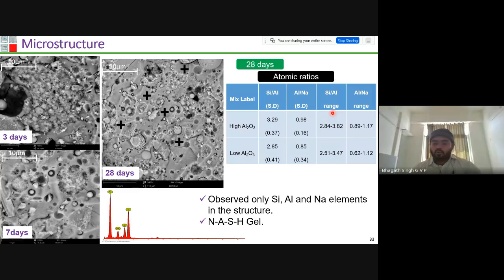And coming to the microstructure at the various total reactive oxide ratios and various days, this is the third day, this is the 7 days, this is the 28 days, at a 10 micron scale and this is at a 30 micron scale. At the 10 micron scale, you can see the cenospheres dissolving. It indicates that at the third day, the cenospheres are dissolving, and the product is already formed here. These particles are dissolved, and the formation will take place around this area.